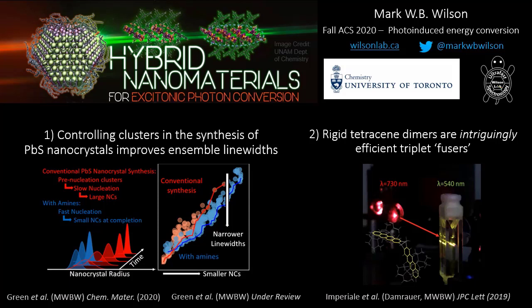In the first, I want to talk about what we've learned about the colloidal synthesis of lead sulfide nanocrystals. We used fluorescent spectroscopy to observe distinct cluster-type intermediates pervasively in the traditional synthesis of lead sulfide nanocrystals. We learned how these intermediates can be controlled using process additives and find that a straightforward extension to the Sugimoto-type models of nucleation and growth accounts for our observations. We apply this understanding to improve, at times significantly, the size dispersity of materials, flattening the energy landscape to improve transport in our devices.